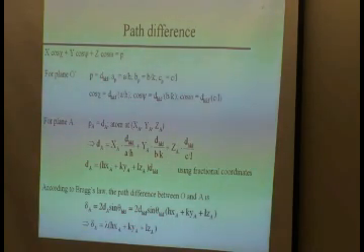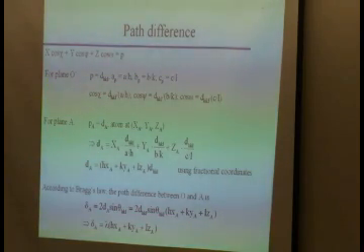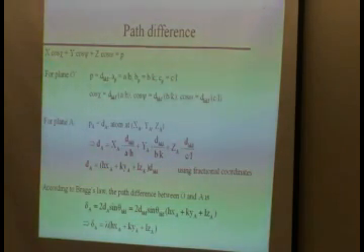And the other thing that we know if we talk about dHKL is that we can use those Miller indices, right? Because where did the plane dHKL cut a unit cell? H, K and L were the reciprocal of the intersections with the lattice constants, right?